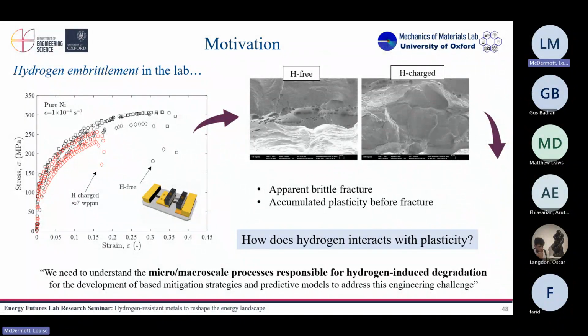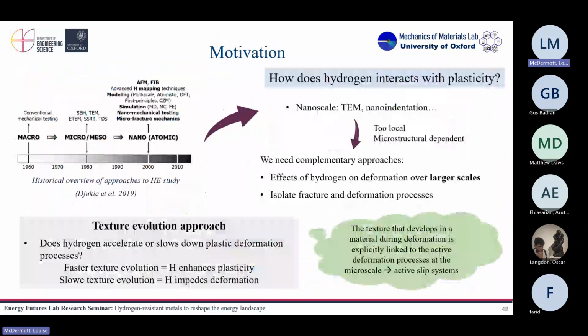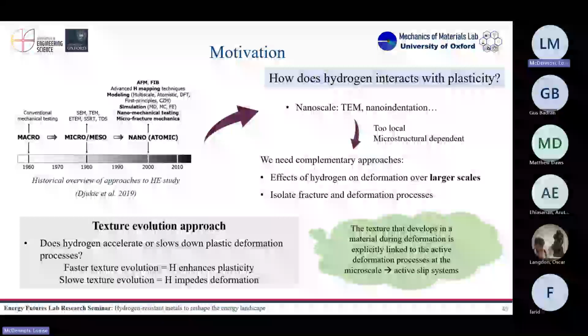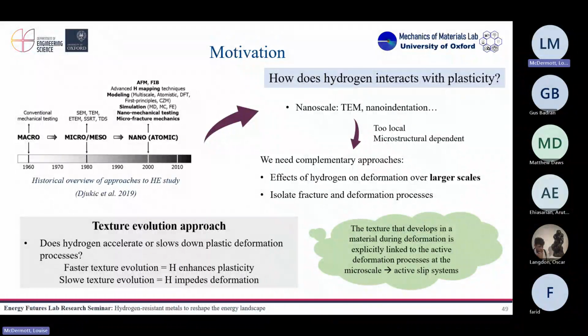Okay. Typically, this kind of research, more fundamental research where we want to study hydrogen-plasticity interactions, has been conducted from a nanoscale, let's say, using techniques that allow you to see a single dislocation or a bunch of dislocations, or an indentation that also targets, let's say, micrometers of your material, right? And we can draw some conclusions from those studies regarding hydrogen and plasticity interactions. But the main problem is that those approaches are very local, and they depend a lot on the place of the microstructure where you study the phenomenon.